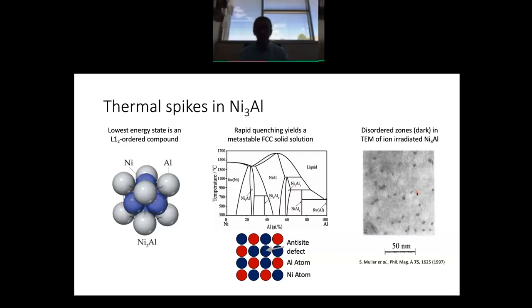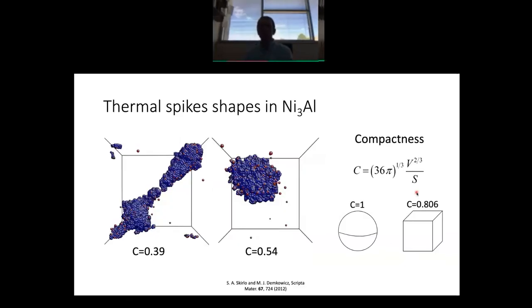So this is a process. This process of thermal spikes in nickel-3 aluminum is something that I studied with one of my former students, Scott Skurlow. Scott did a bunch of thermal spike calculations on nickel-3 aluminum. And one of the things that he noticed is that the thermal spikes have a variety of different shapes. So sometimes they have these sort of elongated needle-like shapes. Other times they have these elliptical or almost spherical shapes. And depending on the kinds of shapes they have, they generate different numbers of defects. Okay, so we did a little study on this and figured out why that happens.